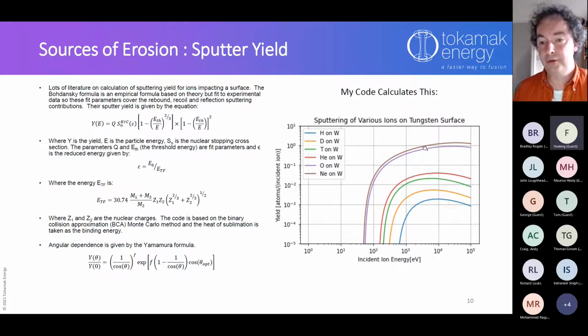So if we get neon and oxygen in the system, and you get up to an energy of a few thousand eV, that'll just basically eat straight through the diverter in a matter of days. Thankfully, here's deuterium, the orange line, and tritium's the green one. These are down to 10 to the minus 2 sort of levels, which is much more manageable.